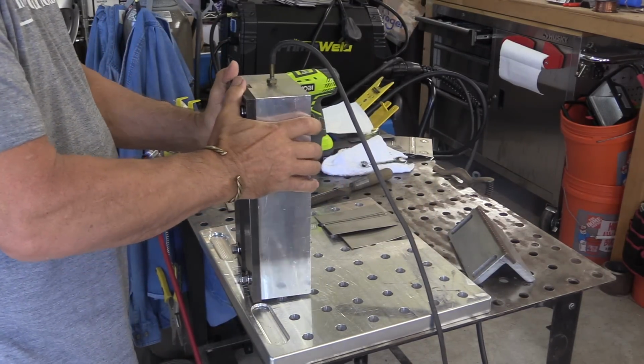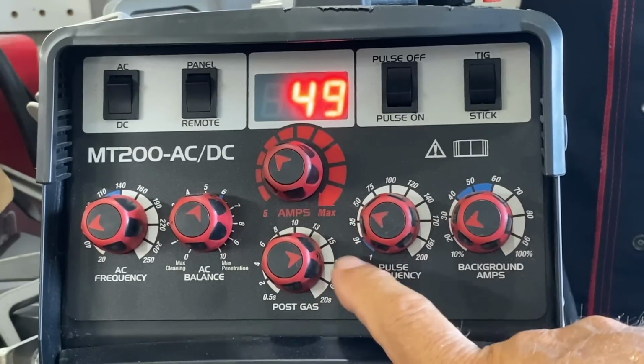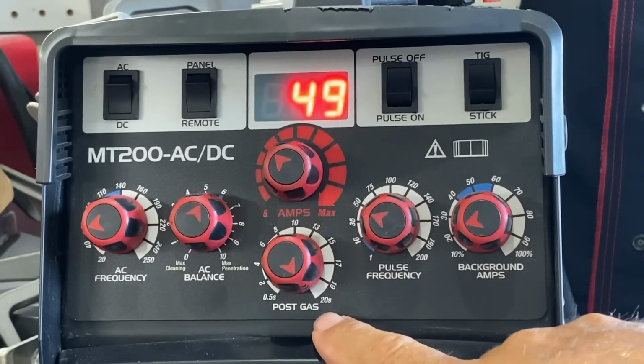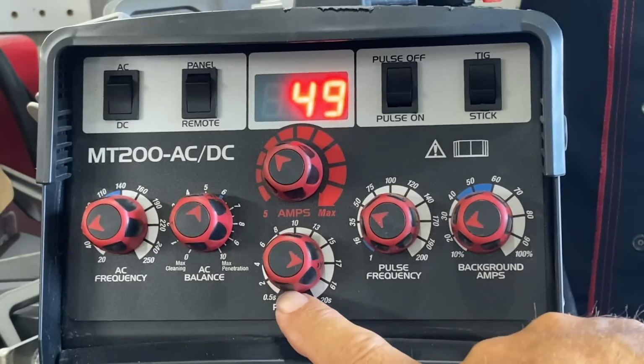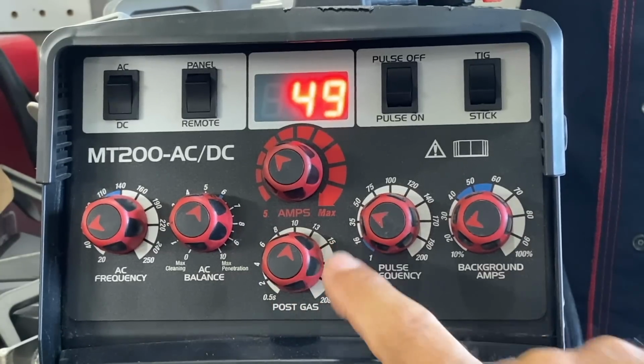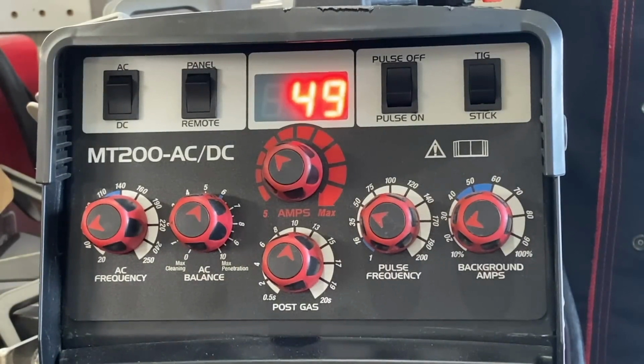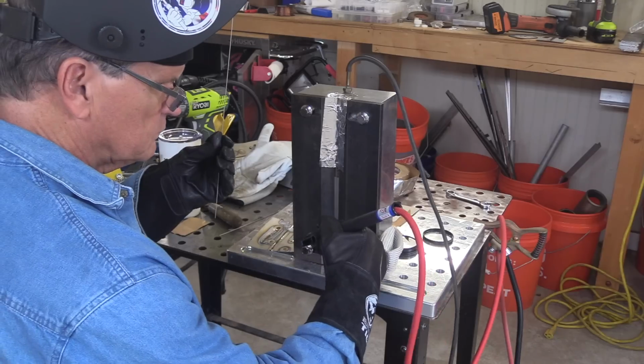try to get comfortable. I'm using the CK MT200 machine. Usually I would set post flow probably to max for titanium, but since I'm welding inside a fixture with all that chill factor, I only need about 10 seconds.